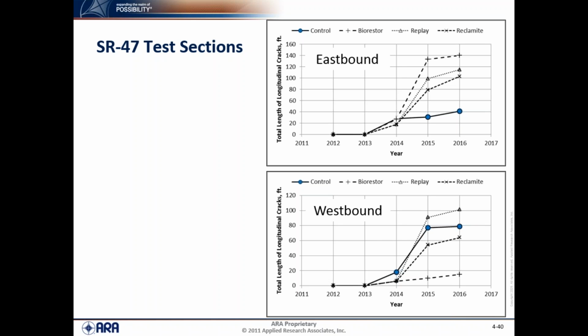Again, we started seeing some of them in 2014, and then in 2015 they started to increase. Even though we showed 2012 here for State Route 47, 2013 is when the sealer was actually applied, and then we started taking our annual measurements after 2013. So on State Route 47, the sealers were applied much later after the AC overlay was placed relative to the US 40 project and these two sections on State Route 292. So there's a difference: there was more traffic applied to the surface prior to the sealer application on 47 than on the other projects.